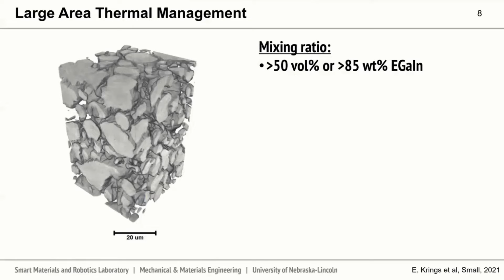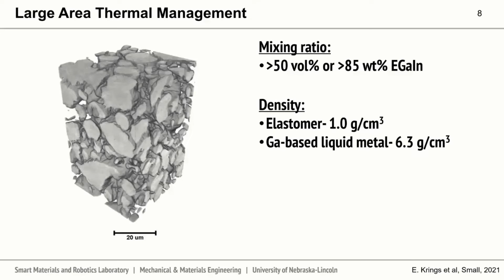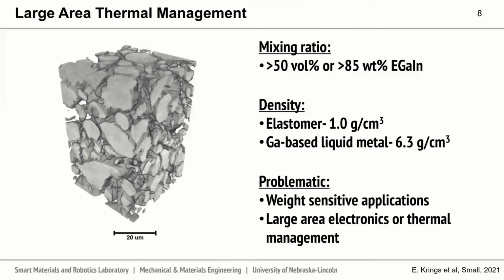What I've shown up to this part is usually to get these highly functional properties, these elastomer composites are typically loaded up to really high volumes, up to 50% by volume, or greater than 85% weight of the liquid metal. This large mismatch in the density of the elastomer and the liquid metal filler is really problematic for weight-sensitive applications, such as aerospace, and also large area electronics and thermal management.